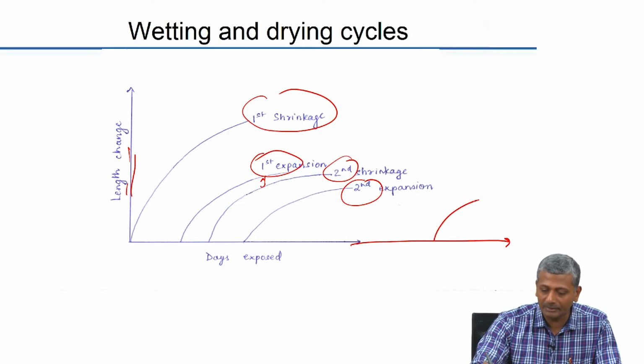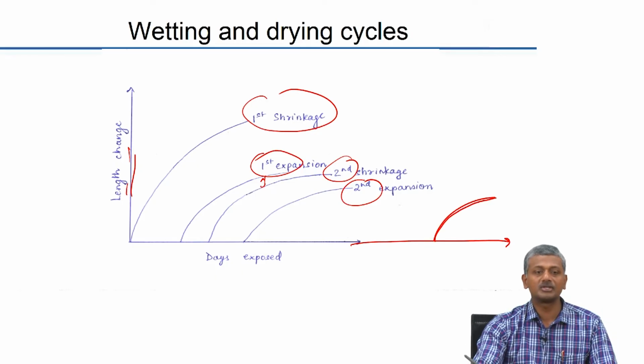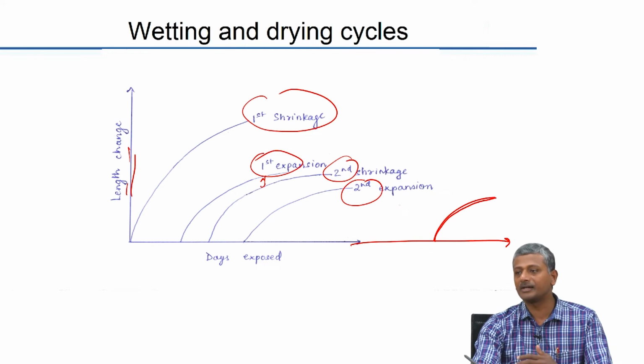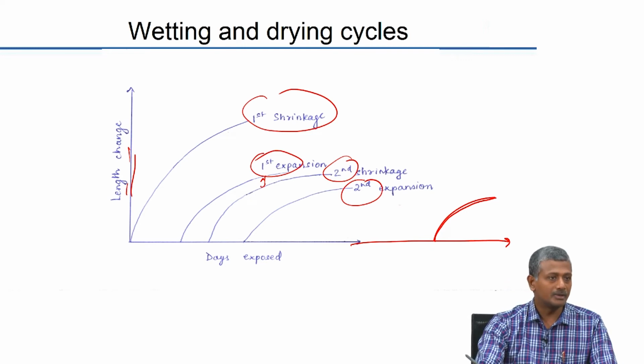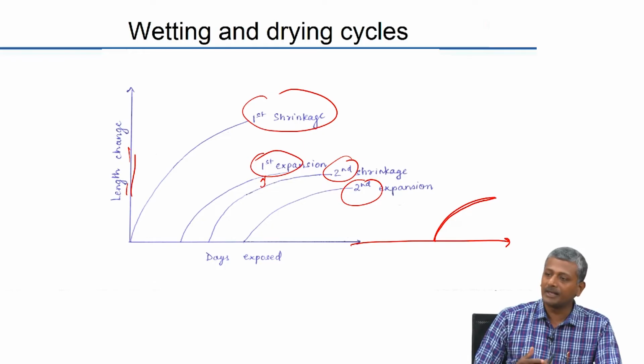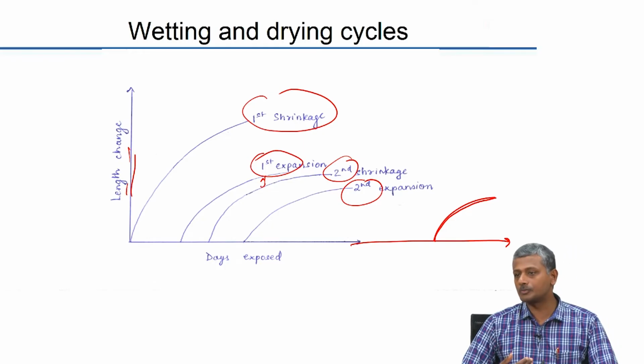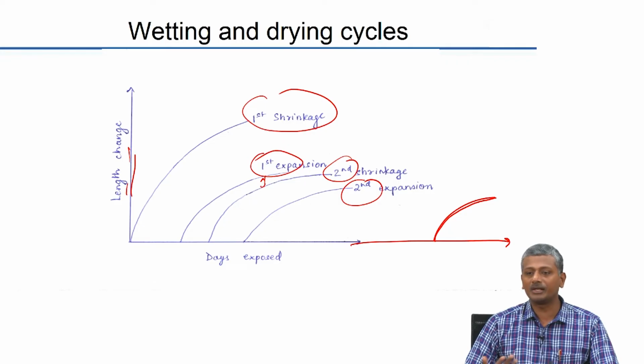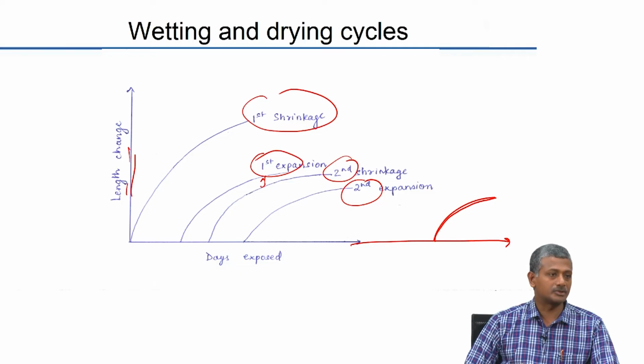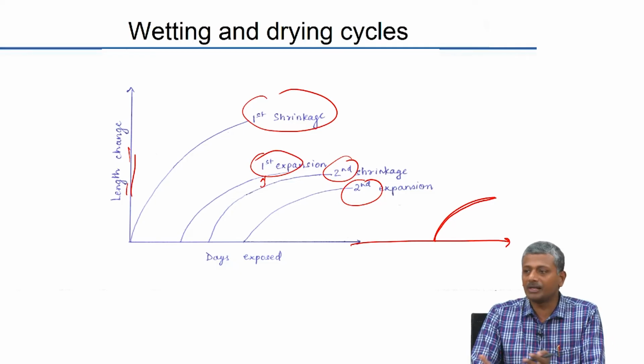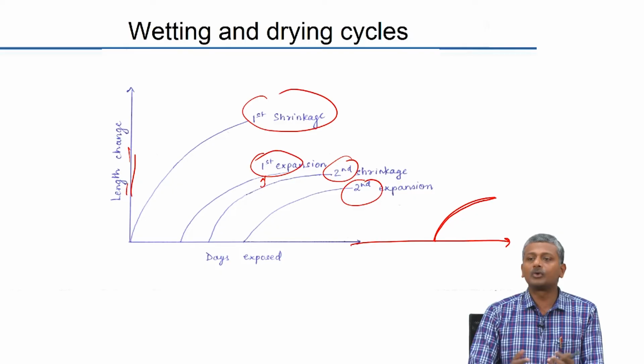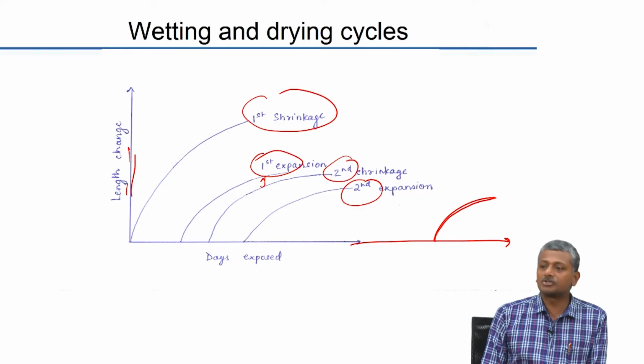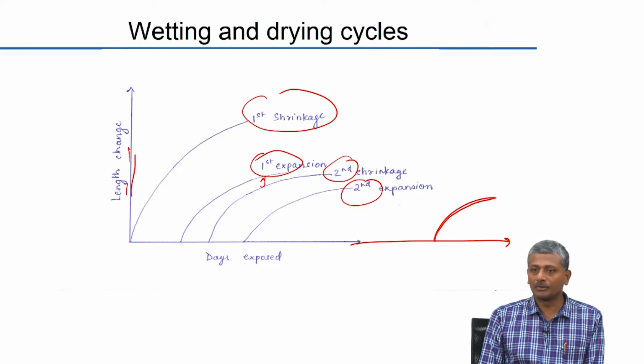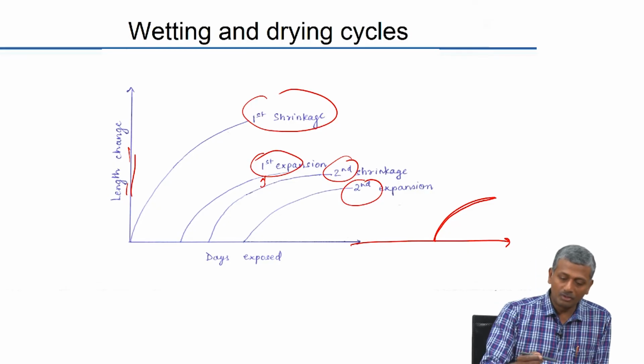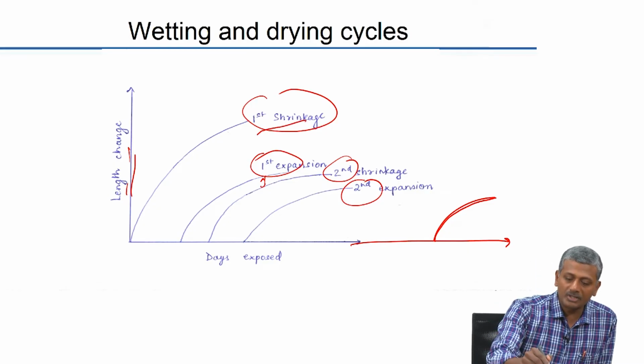What will end up happening is both the curves will coincide. The shrinkage curve and the expansion curve will start coinciding after multiple number of cycles. That means that the water is now capable of only entering certain pores and leaving those pores, and those pores may be large enough to really not lead to a major alteration in the microstructure. So, beyond that point you do not really see a change in the structure, and you do not really see a difference in the performance as far as shrinkage and swelling is concerned. Okay. Nevertheless, it is important for you to understand what happens during this first shrinkage.